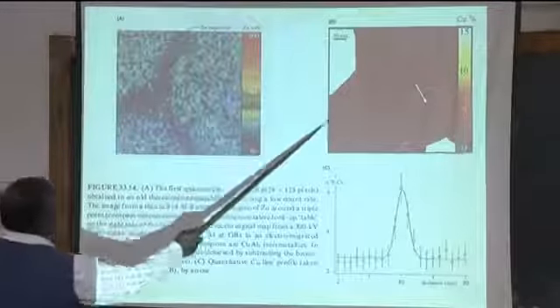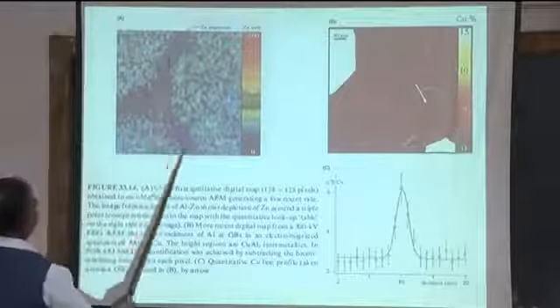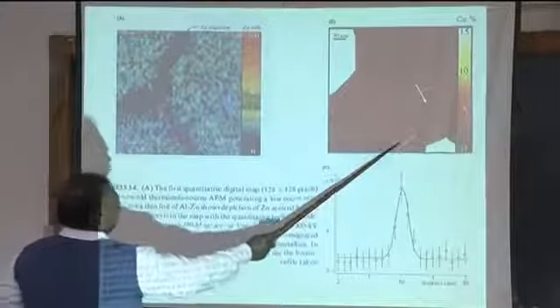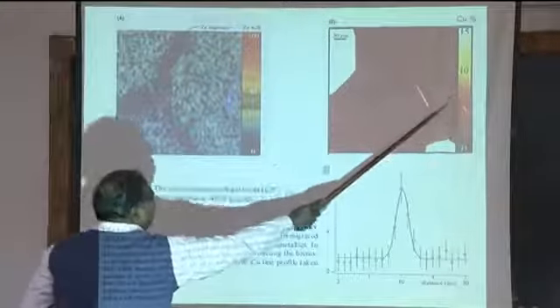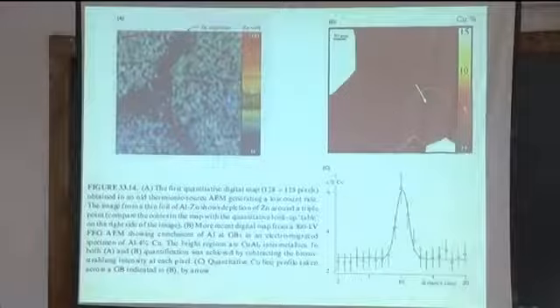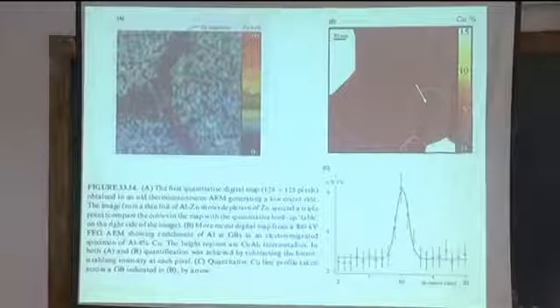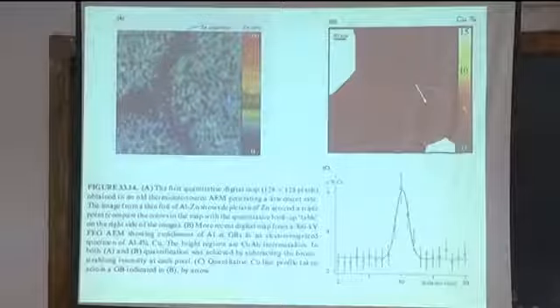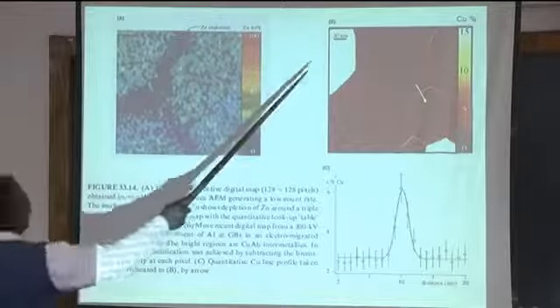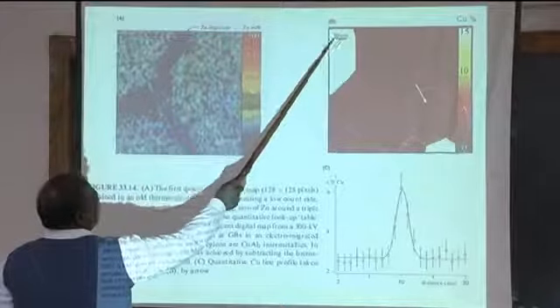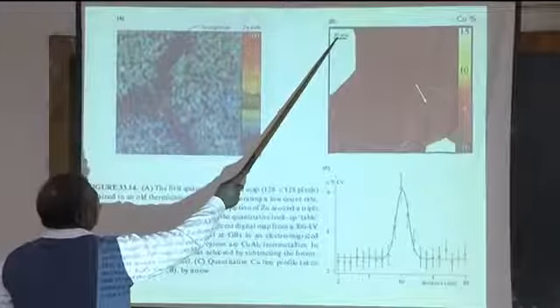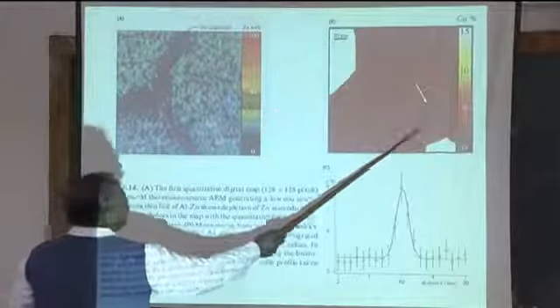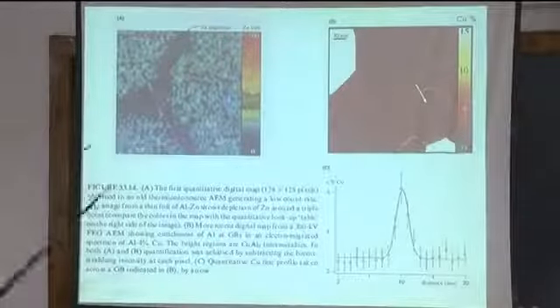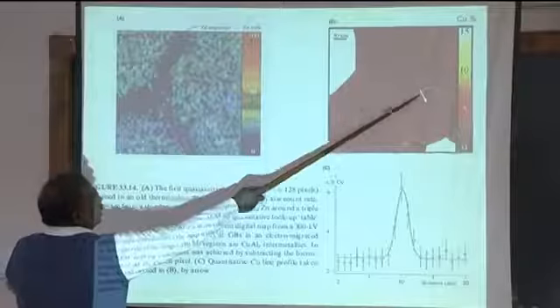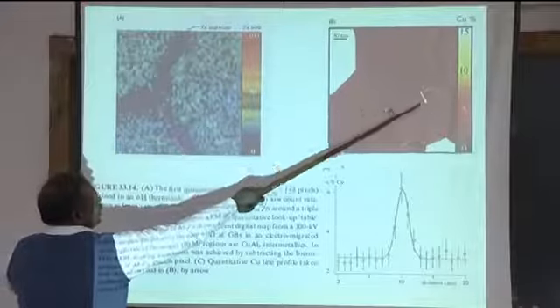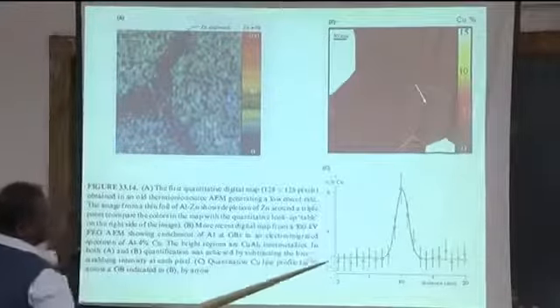And these are the grains. This is the grain boundary. Okay, and these are the grain boundaries as provided by the latest models of EDS analysis systems. See the marker here. This is 30 nanometer. This is the length of 30 nanometer. And that is how you can get this. You can get a line profile. From here to here, you can get your composition variation. That is what is shown here.